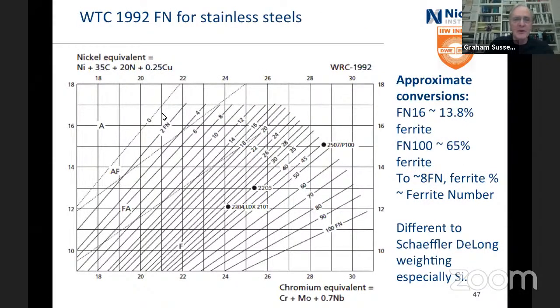And this is what we've got. This is the 1992 WRC, and these are ferrite numbers. And if you want some conversions, well, ferrite number 100 down here is 65% ferrite, approximately. Ferrite number 16, which is up here, is about 13.8% ferrite. And up to about 8, ferrite number and ferrite percent are about the same. So that's right over this side, right in the edge of the ferrite-austenite, just before you get to the austenite-ferrite. And there is a difference to this from the Schaeffler-DeLong, because you'll note that silicon's not down there.